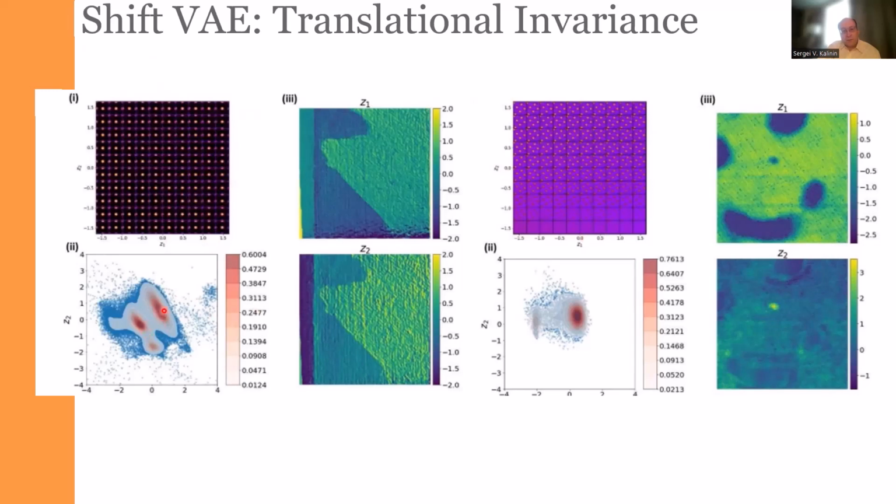Our latent distribution has well-defined maxima, and you can clearly see that our image shows the ferroelectric domains and the three maxima corresponding to one ferroelectric state, another ferroelectric state, and substrate. And for the two-phase material, there are only two maxima as well. So that's actually super interesting.